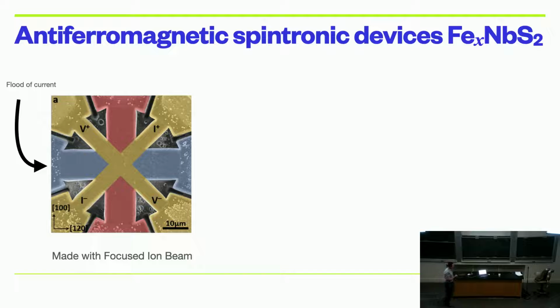Depends on the system, but this particular one was about a micron thick. So you do it just by scotch tape? No. For this particular one, they don't exfoliate very well, so we machined lamella for this one. But there are other systems where you can actually exfoliate them and get even a couple of 100 nanometers or something.